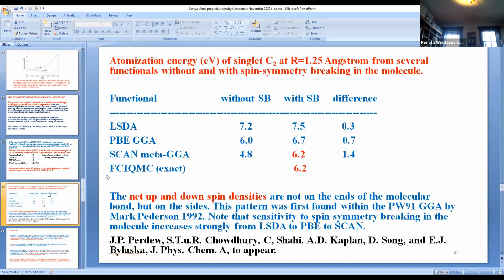On this slide, I show the SCAN results and the results of other functionals for the atomization energy of singlet C2 at the equilibrium bond length, for several functionals with and without spin symmetry breaking. With LSDA, there is a symmetry broken solution, but it only makes a slight increase in the LSDA atomization energy, which is too large anyway.